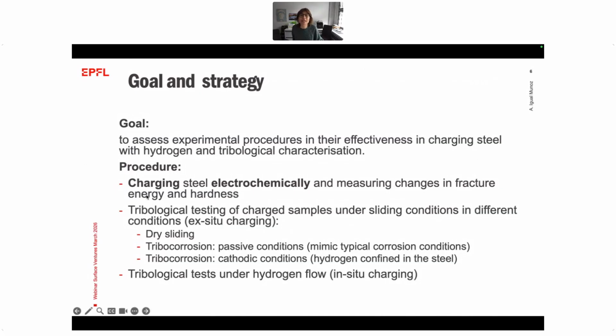So the goal of this presentation is to assess the influence of these experimental conditions when we try to understand the effect of hydrogen-metal interactions. And the strategy is, we come from an electrochemical background, so we use a simple electrochemical setup to charge the material in a well-controlled manner. Then we try to determine if the effect on the material is real. So we can measure changes in fracture energy and hardness, and then we carry out tribological tests under well-controlled surface conditions.